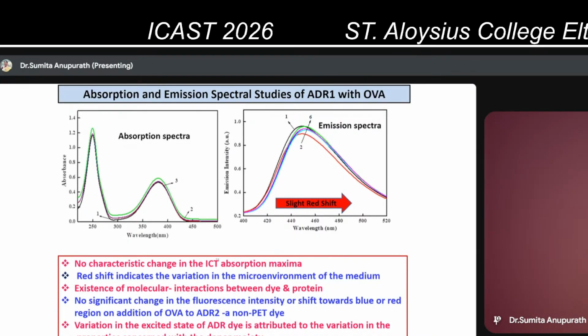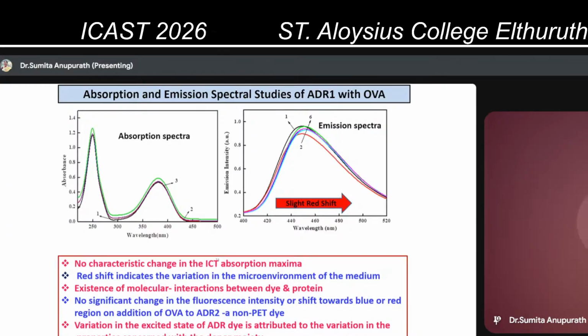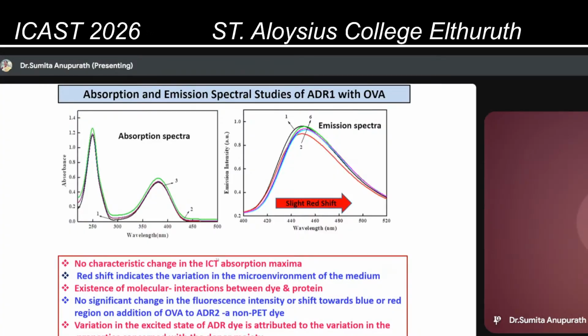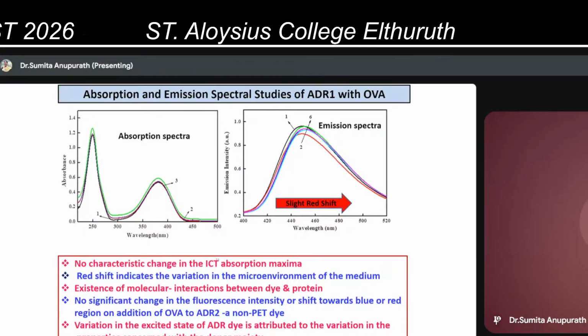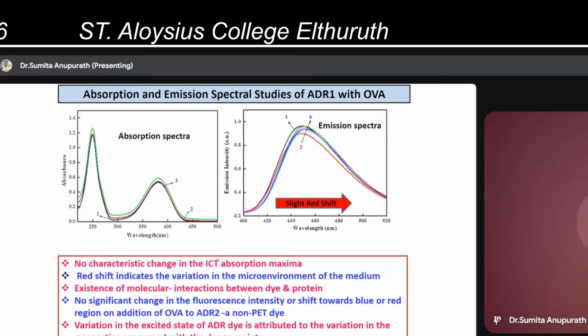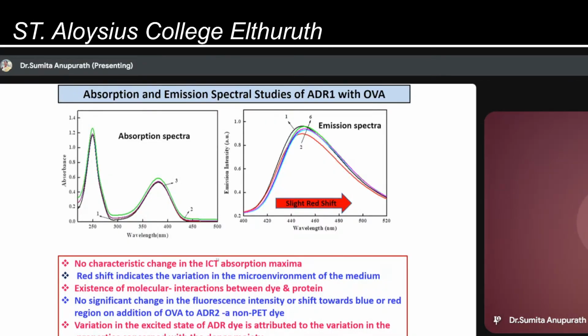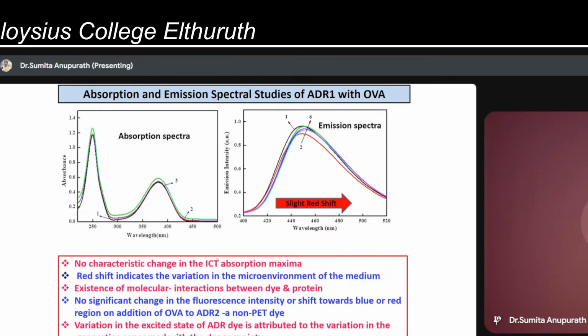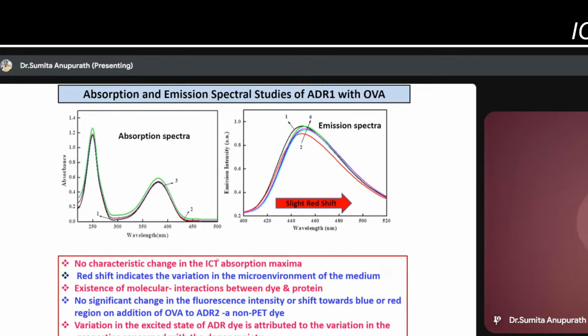But surprisingly, no such changes were observed with the non-PET dye, ADR2. There was no significant change in the fluorescence intensity. There was no shift towards the blue or the red region when ADR2 was treated with ovalbumin. And such changes in the excited state property of the dye are due to its structural differences.